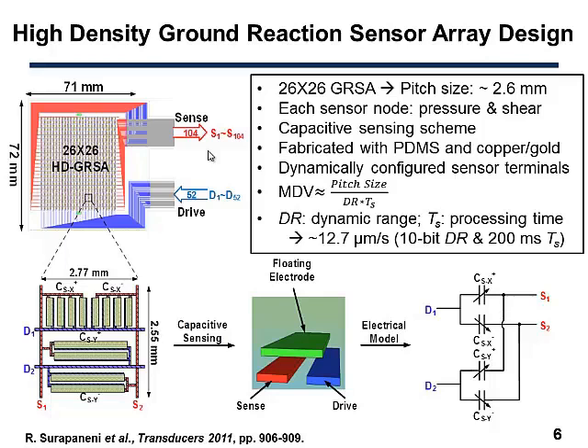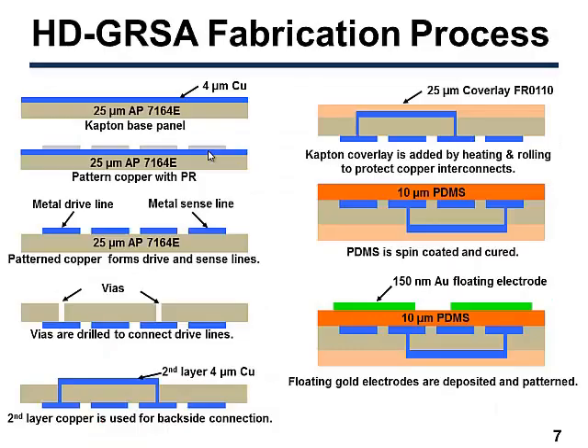The sensor is fabricated with PDMS and copper and gold. The bottom right figure shows an electrical model of our sensor node. The sensor can be dynamically configured to realize x-axis and y-axis shear sensing and z-axis pressure sensing. The minimum detectable velocity (MDV) can be estimated as the pitch size over the dynamic range and the processing time. Given a 10-bit dynamic range and 200 milliseconds processing time, we expect a minimum detectable velocity of about 12.7 micrometers per second. This is our ground reaction sensor array fabrication process.